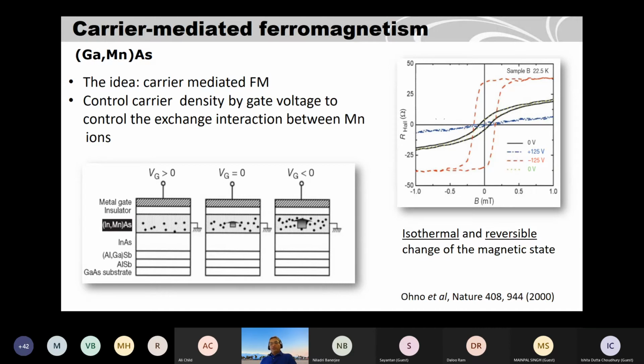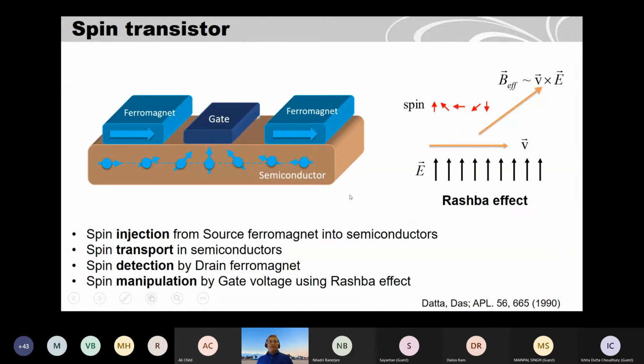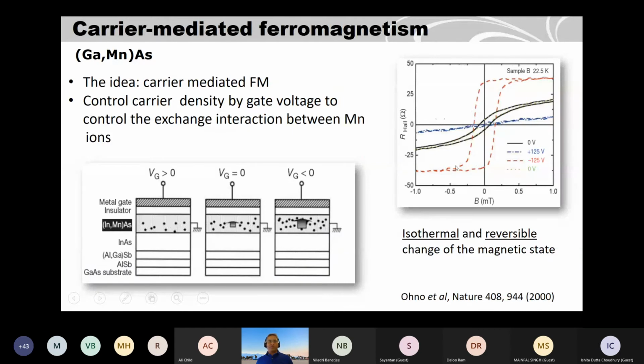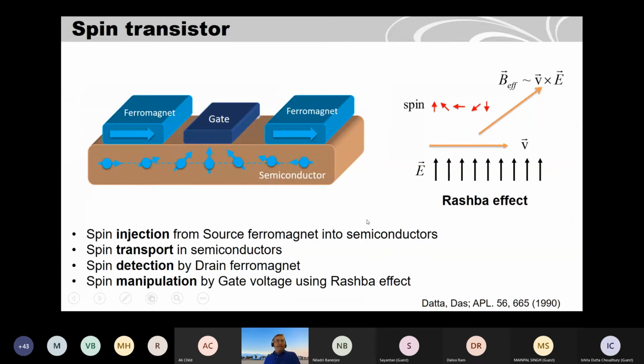But nowadays also it's possible, because if you make a very thin ferromagnetic metal, less than 1 nanometer, you can also change the magnetic properties or tunability with gate voltage. But this you can do also with thick samples. Then the next question was, because the Curie temperature of these diluted magnetic systems was very low, below room temperature, people were thinking how to integrate normal ferromagnets like iron, cobalt, or nickel with semiconductor channels, so that you can inject spins from the ferromagnet into the semiconductor, and the spin can move in the channel. You can detect with another ferromagnet. So for example, this is the source, this is the drain, and this is the channel material.